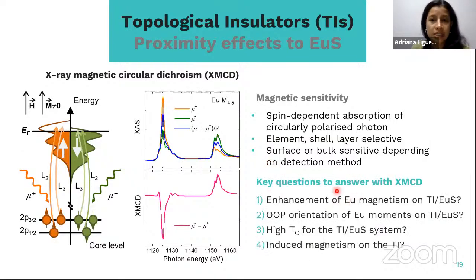So the key questions that we wanted to answer were whether there was an enhancement of the europium magnetism at these interfaces, also about the anisotropy, whether there was an out-of-plane orientation of the europium moments, and whether there was an enhancement of the Curie temperature of the system as reported. And the most relevant result that we wanted to confirm or look for was whether there was an induced magnetism within the TI.